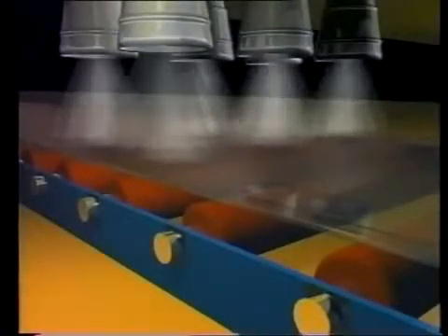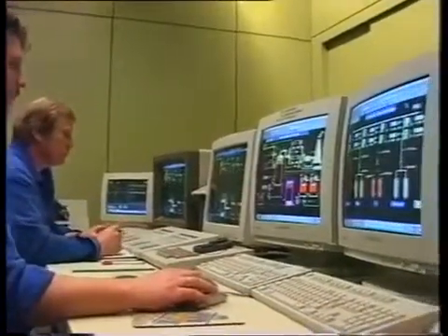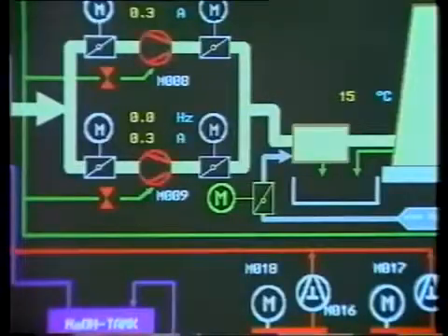Special properties, including the ability to reflect heat, can be imparted by applying an extremely thin metallic layer to the glass while it's still hot. Pilkington K glass, produced in this way, increases the efficiency of double glazing by as much as 50%.